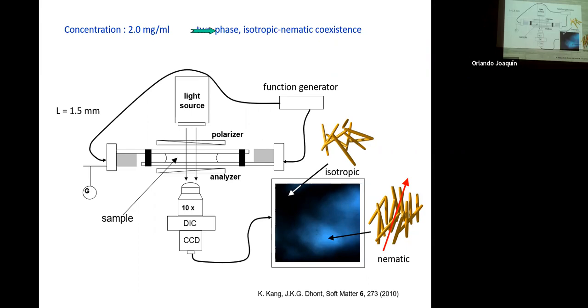And if it is isotropic, there is no preferred alignment. So you would see that it's dark because it corresponds to the polarizer. So there is no light coming through if it is isotropic. If it is nematic, because of the birefringence of the rods, the polarization direction will change. And then you will find a finite intensity. So everything that is bright corresponds to a preferred direction.